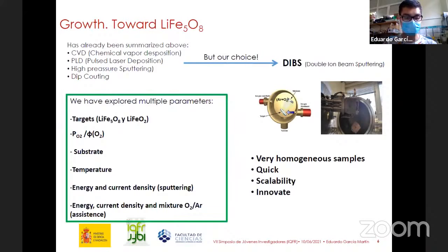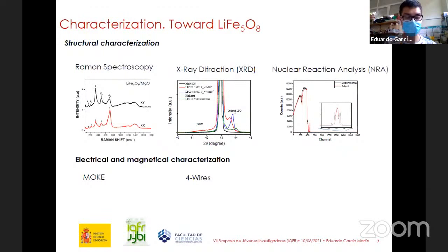This technique allows growing very homogeneous samples of high crystalline quality. We explored several parameters like target, partial pressure of oxygen, substrate temperature, and energy and current density of sputtering and assistance. Regarding the characterization of the sample, we use structural characterization techniques like Raman spectroscopy, X-ray diffraction, nuclear reaction analysis, Rutherford backscattering, and for the electrical and magnetic properties, we use MOKE, magneto-optical Kerr effect, and four-wire measurements for properties like resistivity.